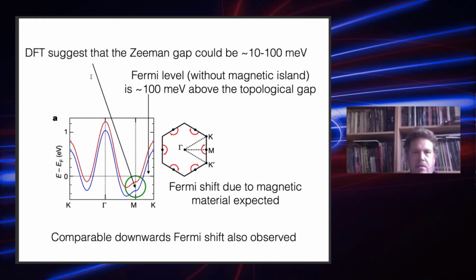And here we see the DFT suggests that the Zeeman gap could be of the order of 10 to 100 meV. So we don't really have a good handle on what is the appropriate size, but we know that it realistically could be tens of meV. And also we see that the Fermi level without the magnetic islands, in the pristine system, is something like 100 meV above the topological gap.